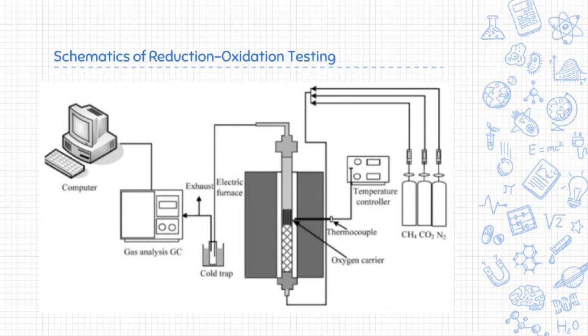We used 3 gases: nitrogen, methane, and carbon dioxide. Nitrogen was used to create a constant atmosphere in the metal pipes, which ran through a furnace box and connected to a cold trap and gas chromatography, which sent the data to the computer. The membrane can also be called the oxygen carrier.